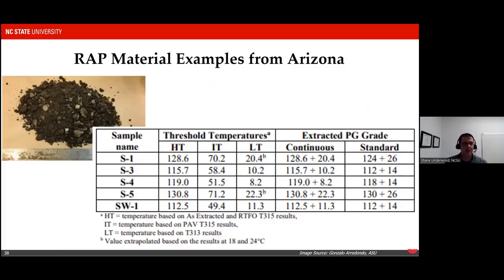Here's another example from the state of Arizona. Again, 5 samples taken from the same wrap stockpile. And here you can see the continuous PG grade varies from as low as 112 up to 130. This is actually extreme. Now, Arizona is much more arid. It is much hotter. Usually in the city of Phoenix, if any of you have been, you know this, the city gets into the 40s, 40 degrees Celsius or 45 degrees Celsius in the summer. So it's very, very hot, and that causes the wrap to be different.